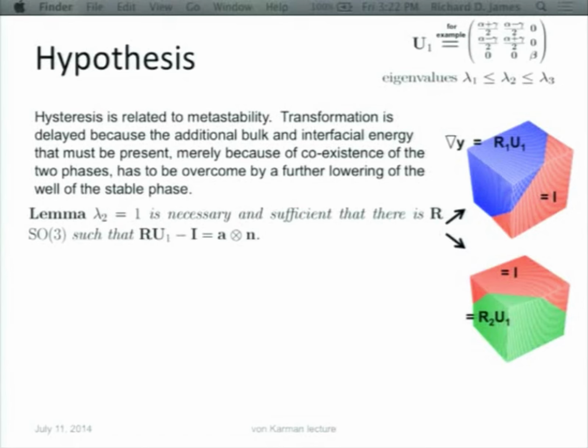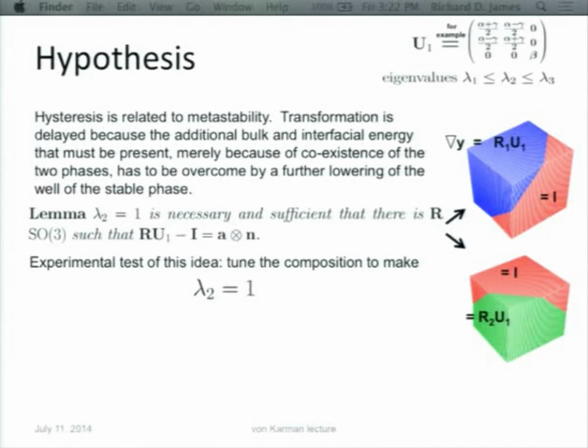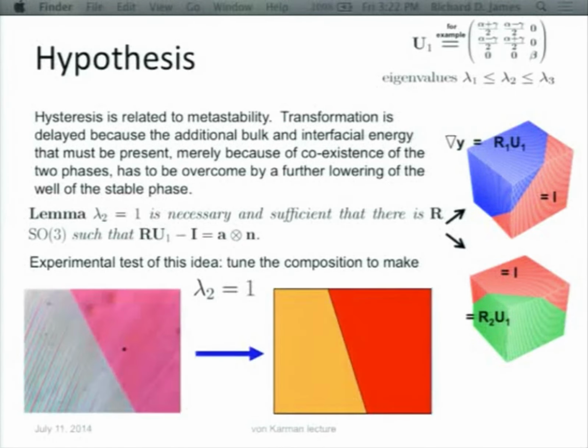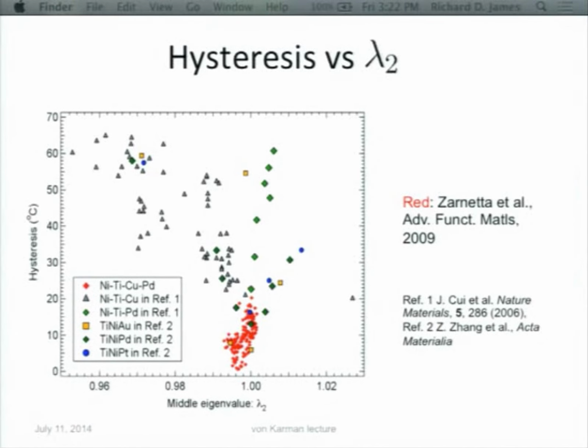And if you believe that the energy due to that interface, or to that delocalized interface, is what's causing the barrier for hysteresis, then what you should do is experimentally tune the lattice parameters of the material by changing composition so that lambda 2 equals 1. Okay, so we did that. And this is, in fact, this combinatorial data. And the result was absolutely astounding.